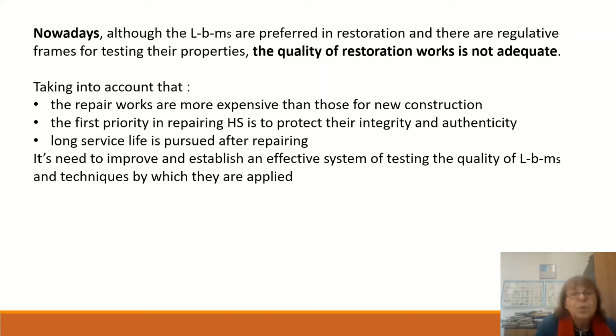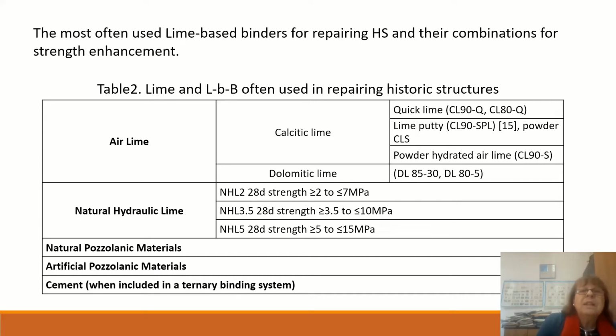We need to improve and establish an effective system of testing the quality of lime-based mortar and the techniques by which they are applied. Here are the most often used lime-based binders and their combinations for strength enhancement. We have calcitic lime, dolomitic lime categories, hydraulic lime categories, natural pozzolanic materials, artificial pozzolanic materials used in combination with lime, of course, and also cement, because very often we use ternary binding systems consisting of lime, pozzolan, and a dosage of cement.